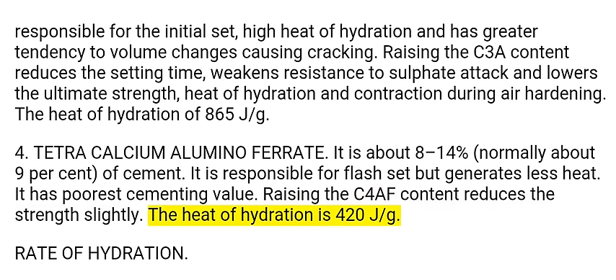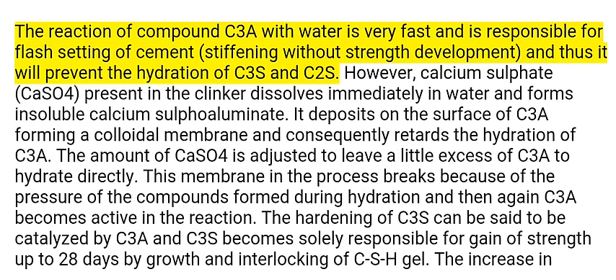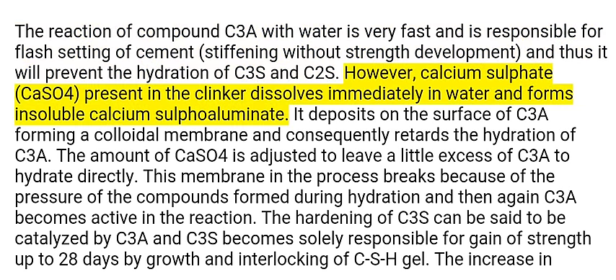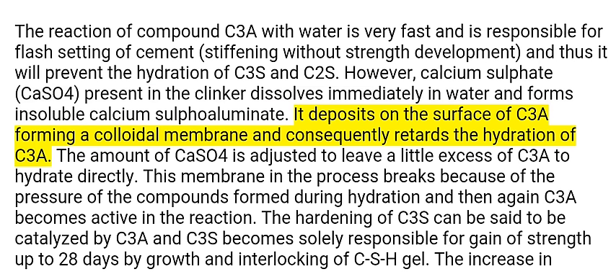Rate of hydration. The reaction of compound C3A with water is very fast and is responsible for flash setting of cement, stiffening without strength development, and thus it will prevent the hydration of C3S and C2S. However, calcium sulfate present in the clinker dissolves immediately in water and forms insoluble calcium sulfoaluminate. It deposits on the surface of C3A forming a colloidal membrane and consequently retards the hydration of C3A. The amount of calcium sulfate is adjusted to leave a little excess of C3A to hydrate directly.